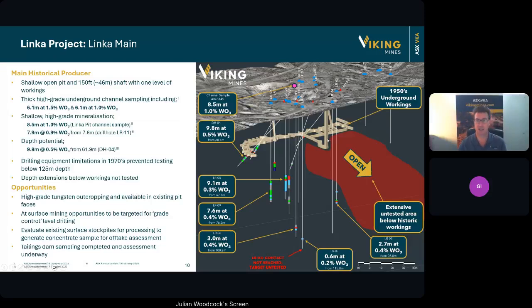There's also deeper holes that we have here, 9.8 meters at 0.5, just underneath the historical workings that shows the mineralization continues under the stope, as well as other holes in the image here, which show 9.1 meters at 0.3%, 7.6 at 0.4, and that shows that the system is continuing with depth.